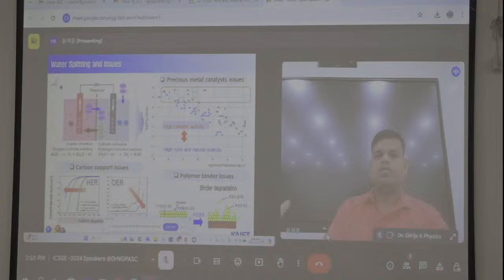When we apply some potential, the water is split: on one side hydrogen evolution happens, and on the other side oxygen evolution happens, because the hydrogen evolution side is the cathode and the oxygen evolution side is the anode. So what is the problem in the commercial aspect of the water splitting technology in industry? Water splitting technology uses platinum or iridium based catalysts, but the cost is very high and scarcity is another issue, because availability on earth is very limited. You can see commercial platinum carbon has a carbon support, like amorphous carbon support.